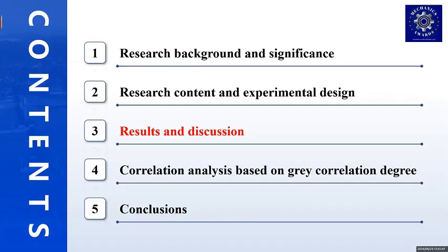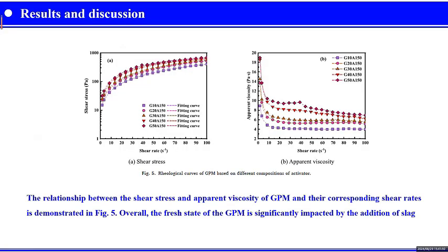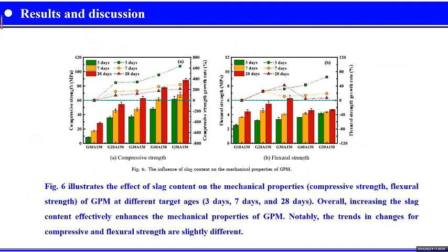The third is results and discussion. The relationship between the shear stress and the apparent viscosity of mortar and their corresponding shear rates is demonstrated in the figure. The figure illustrates the effect of slag content on the mechanical properties, compressive strength and flexural strength of mortar at different target ages. Overall, increasing the slag content effectively enhances the mechanical properties of mortar.